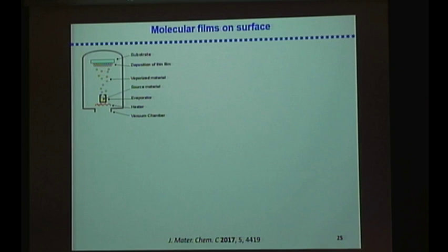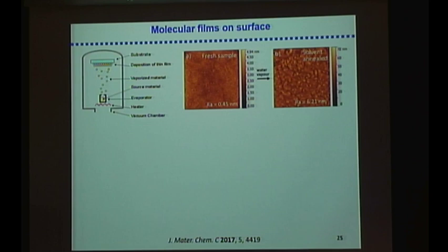As the complex is neutral and has a low molecular weight, we can imagine preparing its film by thermal evaporation of the molecule under reduced pressure. When we remove the substrate from the evaporator, we obtain films, and these films are pristine films. The association of humidity treatment and thermal treatment allows us to switch from a pristine, amorphous film to a crystalline film.